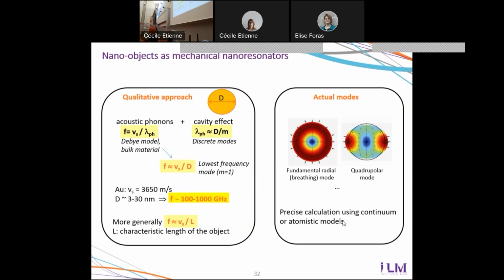and the wavelength can be only approximately the size of the particle, or the size divided by an integer. So it means that the vibrational frequencies are at least of the order of sound velocity divided by diameter. And when you put in the numbers for particles of the order of 10 nanometers, the frequency will be from 100 gigahertz to about 1 terahertz. Of course, it's just to realize the range of frequencies we are dealing with. This can be made much more precise for a given object by numerical calculations of the vibrational modes.